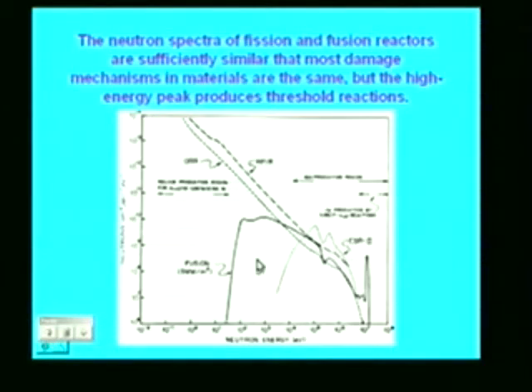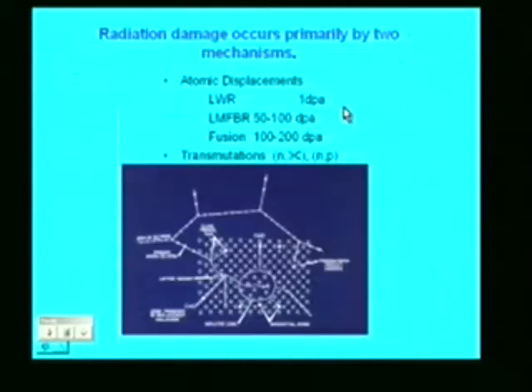And what we notice is that in the mid-range, where a lot of the damage takes place, the spectra are very similar. But in the fusion reactor, we do have a spike at the neutron birth energy at 14 MeV. So to summarize, the neutron spectra of the fission and fusion reactors are sufficiently similar that most damage mechanisms in the materials are the same, but this high energy peak produces threshold reactions.